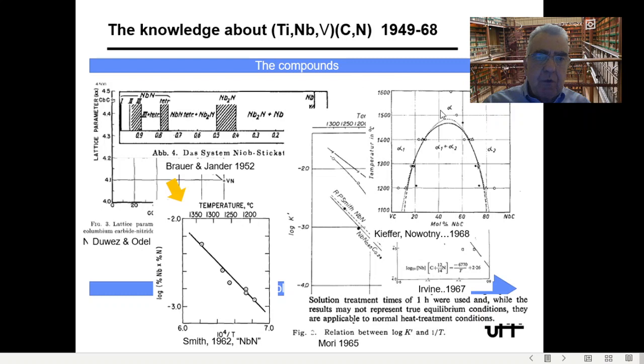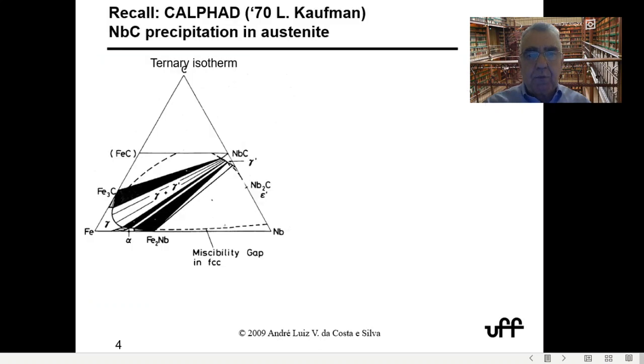Further continuing on the compounds, the people at Plansee did this very interesting work, and they realized that some of the carbides, like vanadium carbide and niobium carbide, had a miscibility gap at some temperatures. So the high temperature miscibility could disappear at lower temperature. We're talking about 1200 C, not that low temperatures.